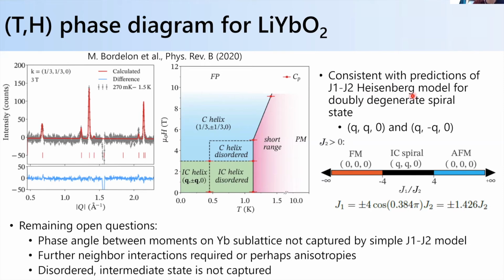So they adapted their old model for a cubic diamond lattice. And it found that indeed the model predicts a doubly degenerate spiral state with Q0 and minus Q0. And so they built a phase diagram showing which state you're in, antiferromagnetic with Q equal to 0 versus ferromagnetic versus this incommensurate spiral state, dependent on the ratio of J1 over J2. And so those are the nearest neighbor and next nearest neighbor exchange couplings.